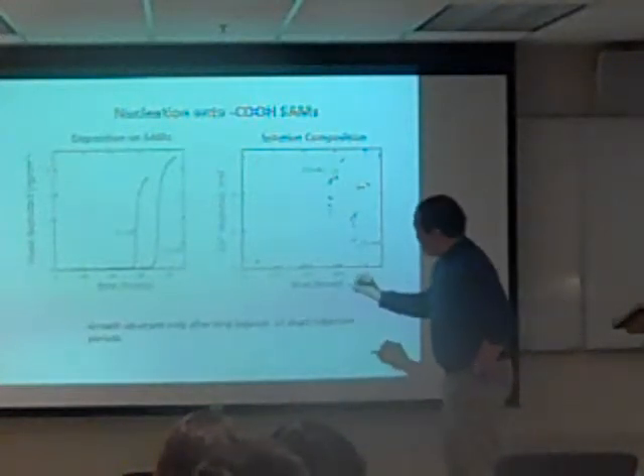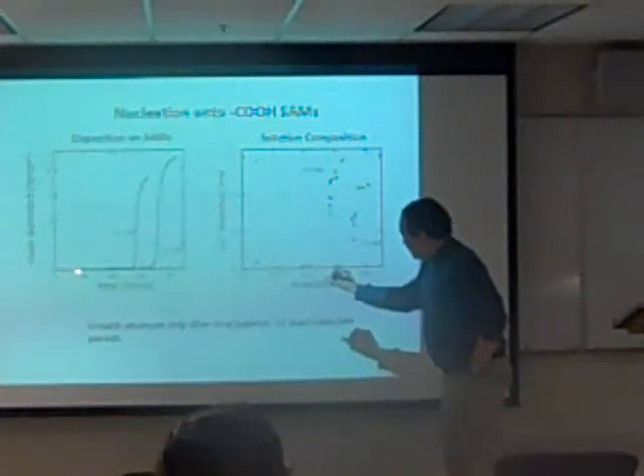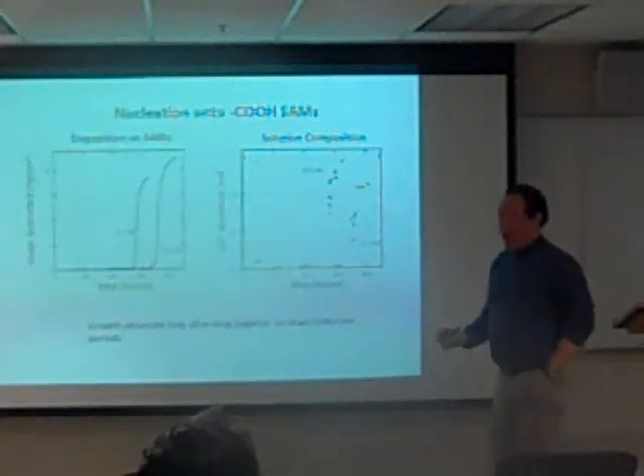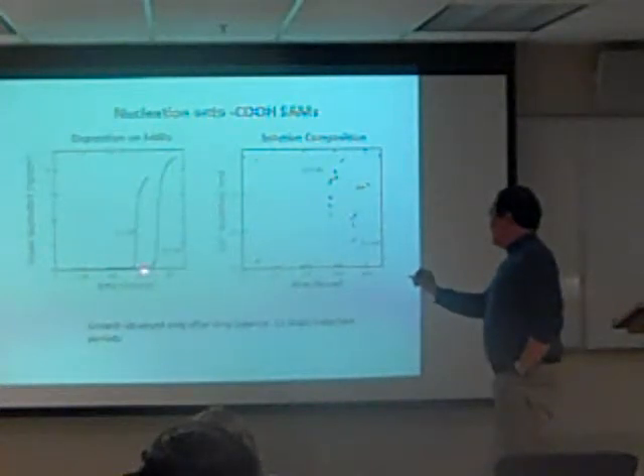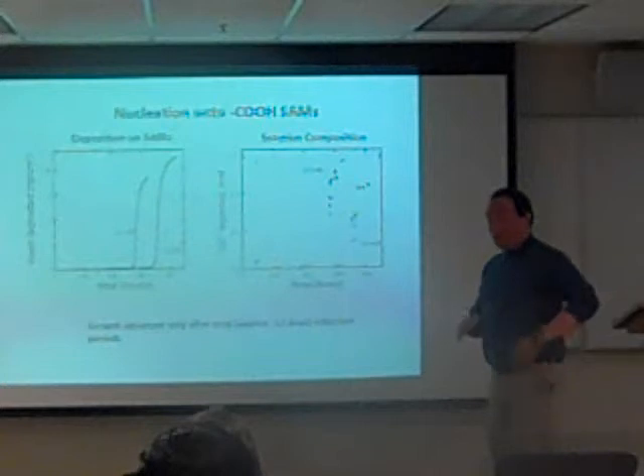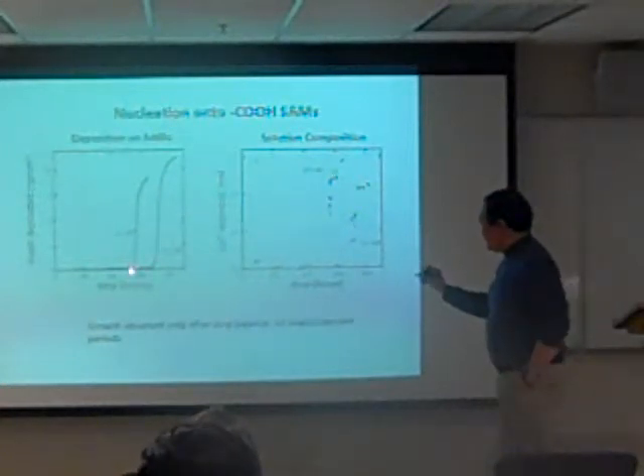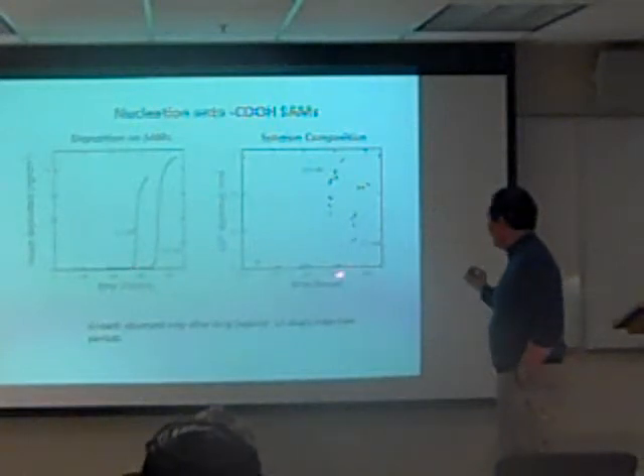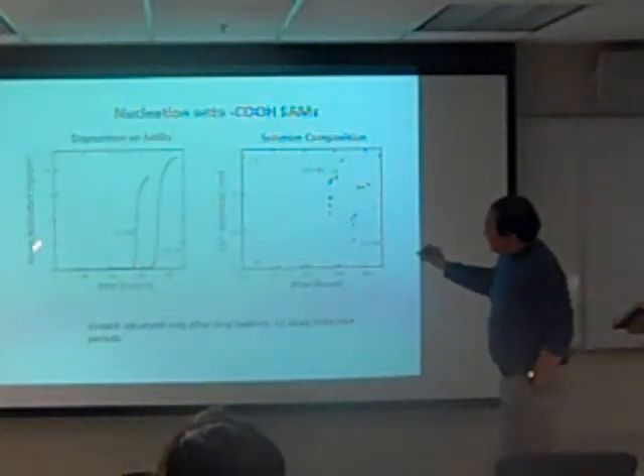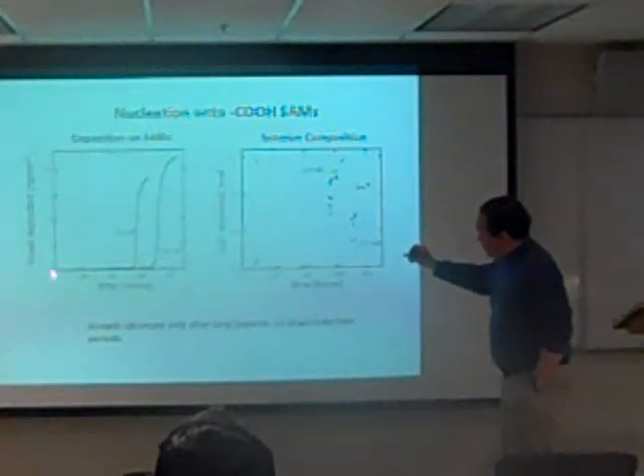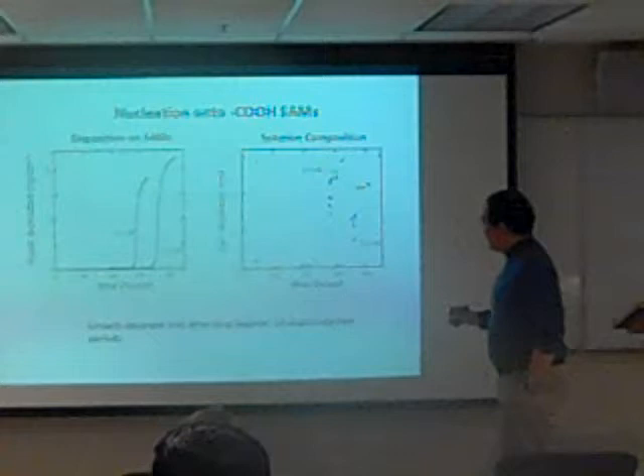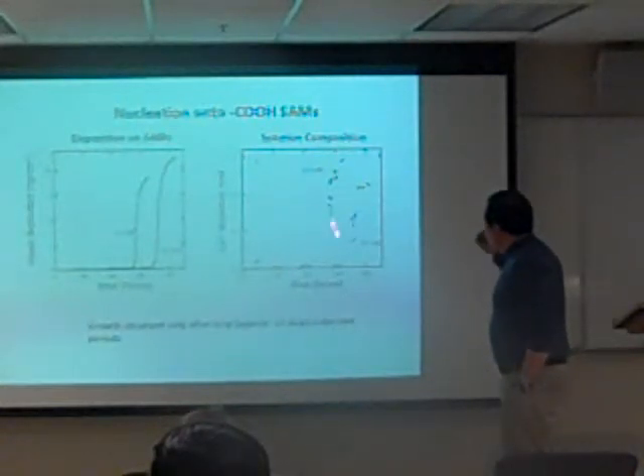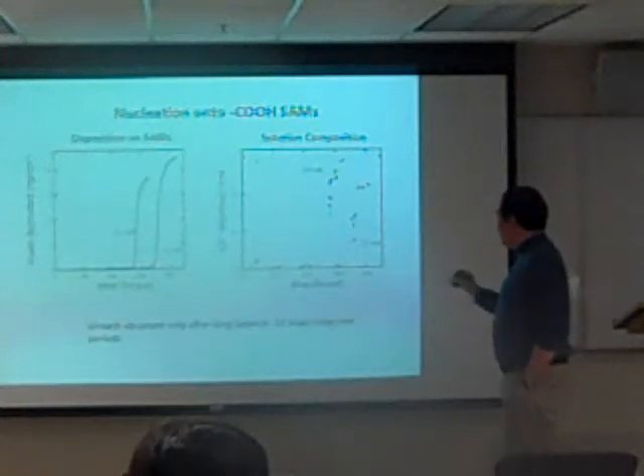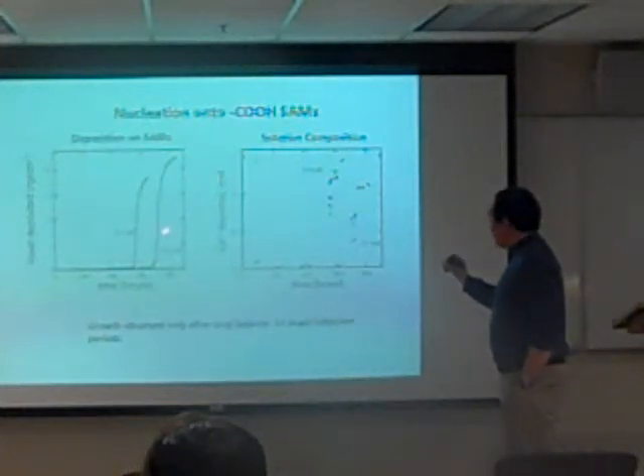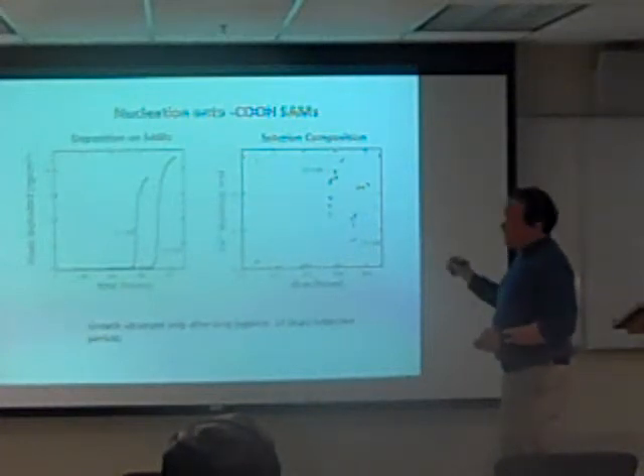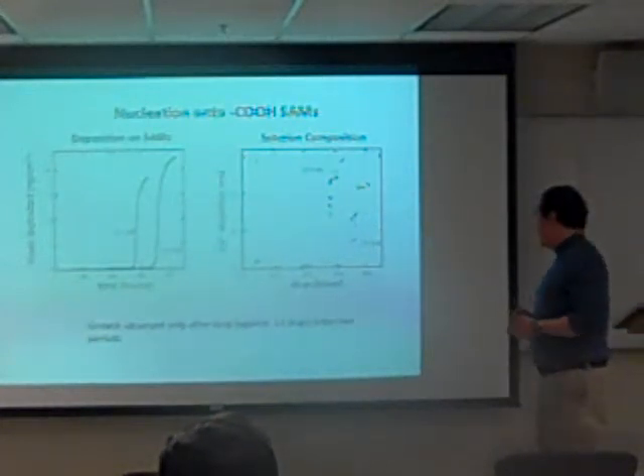It turns out that we needed to do this reaction for a longer period of time. So we actually saw that the mass started to change rapidly after about 200-some hours, or almost 300 hours, basically 12 days. And so this is with the data from the quartz crystal microbalance. So all of these are data points from the quartz crystal microbalance, and this is data from the solution composition from the constant composition apparatus. So we can see that there's a very good correlation between the change in mass and also the ions, where depletion of ions corresponds to growth on that surface.